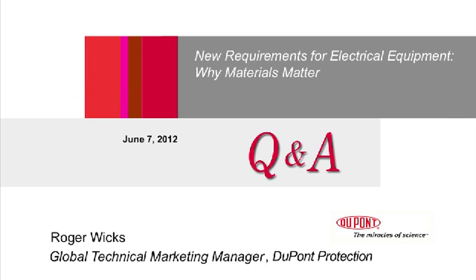I've seen use in some applications in a mechanical press, for example, at a printing press where Kraft type papers were replaced with Nomex papers because the Kraft papers were wearing too quickly. We replaced those and used Nomex paper instead, and dramatically increased the amount of time between shutdowns where they had to replace the backing material. Not sure if those factors apply to the question, but hopefully that'll be some good information.